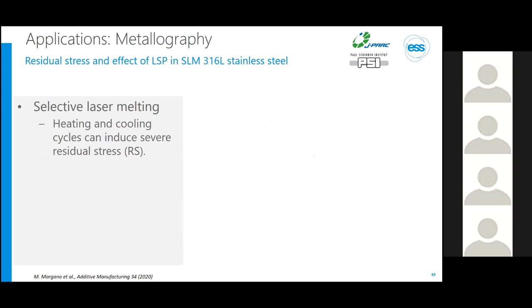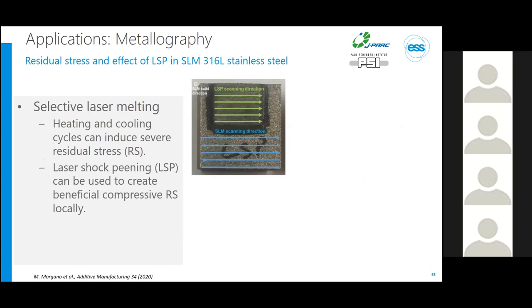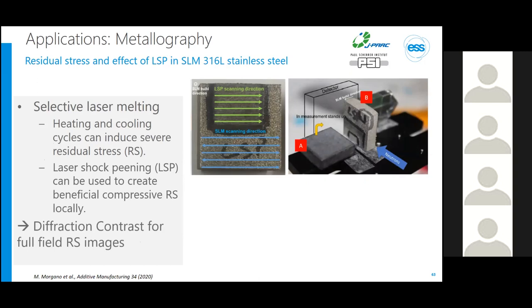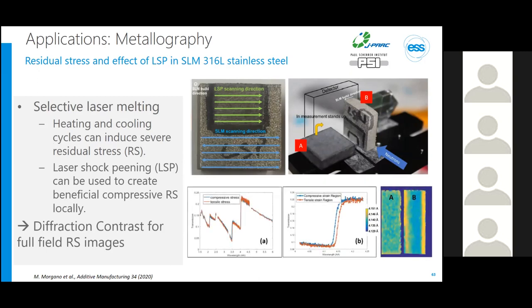In this first study, we looked at residual stresses in selective laser melted stainless steel samples. One method to tackle problematic residual stresses in components in general is laser shock peening, where beneficial compressive residual stresses can be introduced by this process. We then applied neutron diffraction contrast imaging with the goal to obtain full field residual stress images. And we did this at the J-PARC neutron spallation source in Japan.